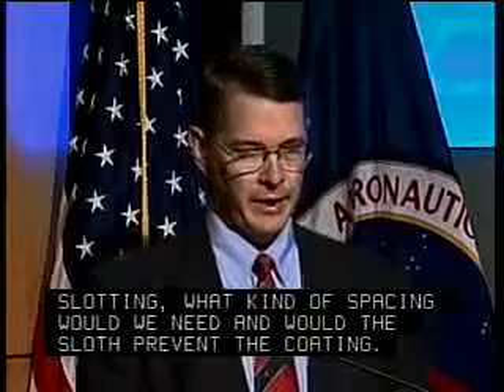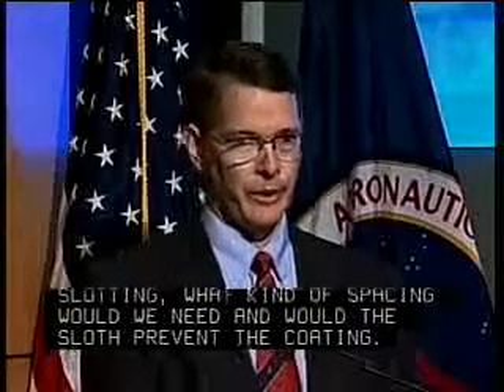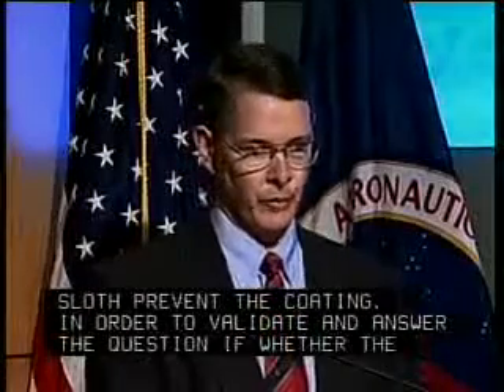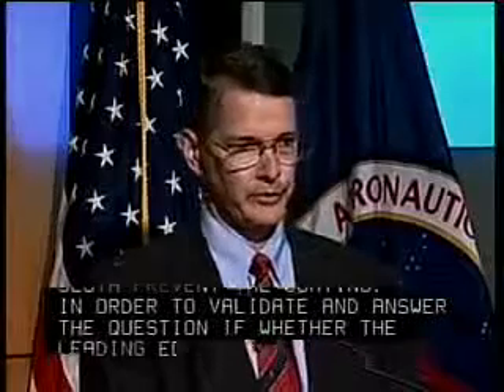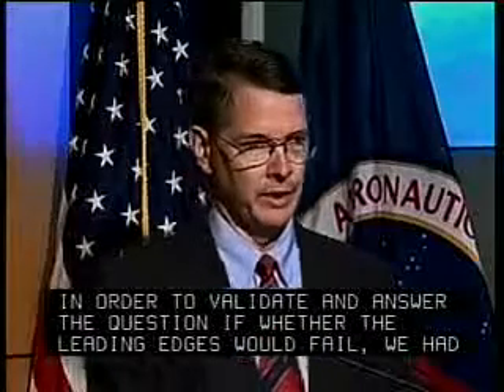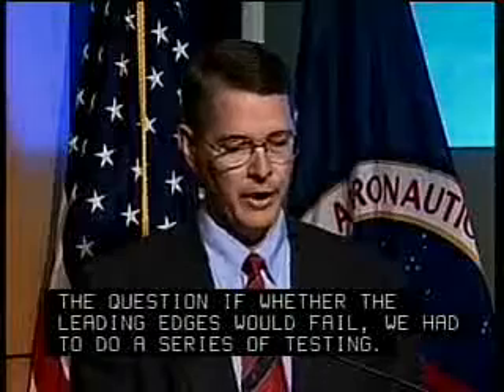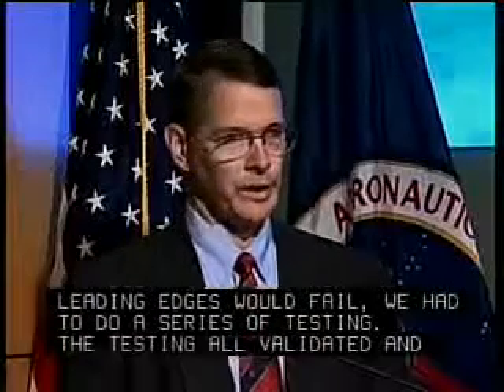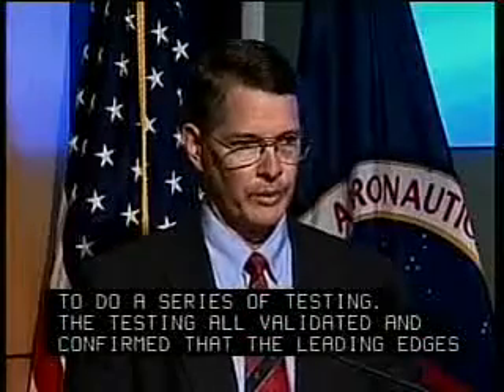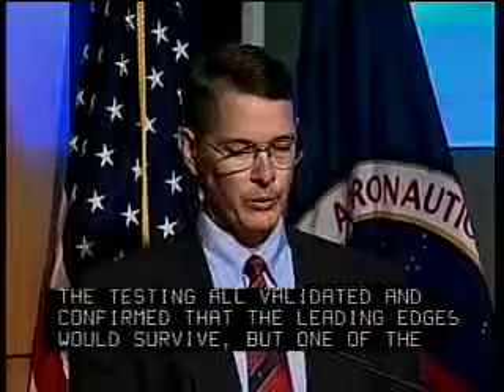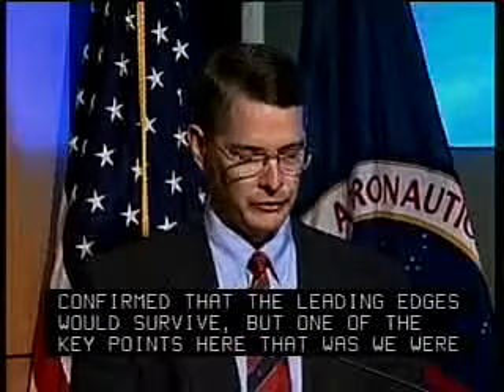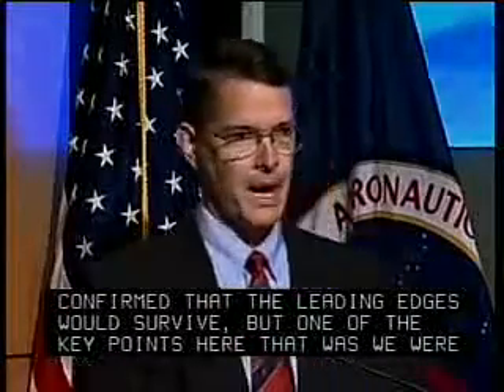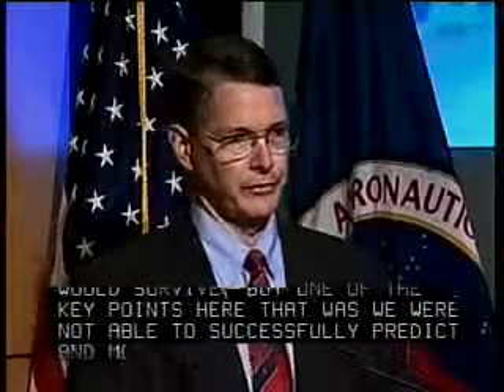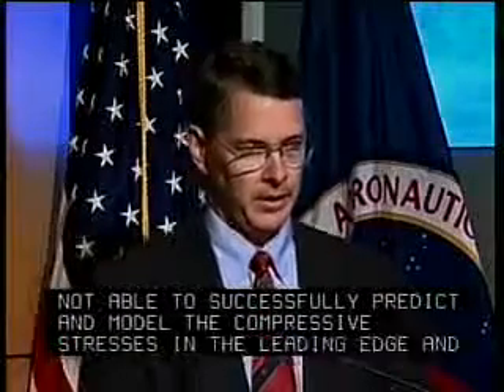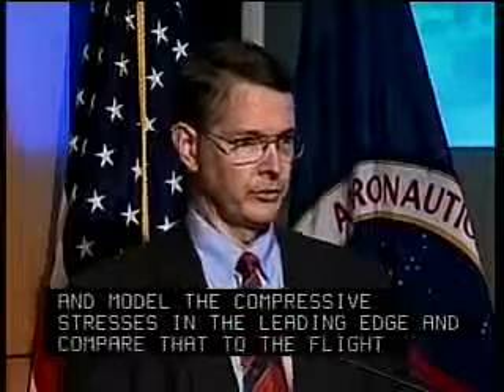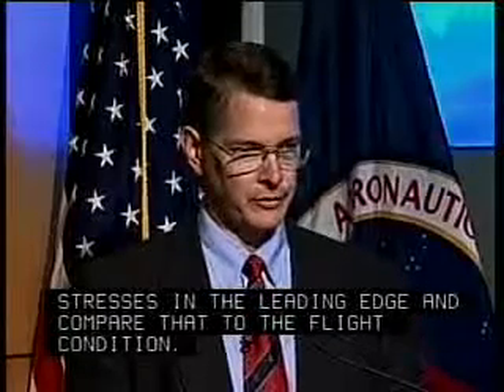In order to validate and answer the question of whether the leading edges would fail due to compressive stresses, we had to do a series of testing. The testing all validated and confirmed that the leading edges would survive, but one of the key points here was that we were not able to successfully predict and model the compressive stresses in the leading edge and compare that to the flight condition. Next chart, please.